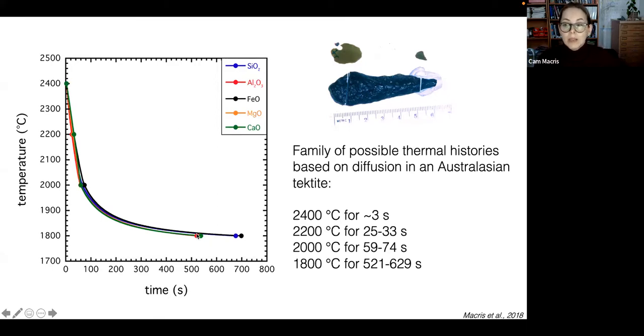What we can glean from this is that this particular tektite that I showed you earlier could have been buffered at high temperatures in an impact plume for about 3 seconds if it was at 2400 degrees Celsius, for about 30 seconds if it was at 2200 degrees Celsius, for a little over a minute at 2000, and much longer times if it was at 1800. These much longer times are really not realistic based on expectations of velocity and trajectory of these tektites.